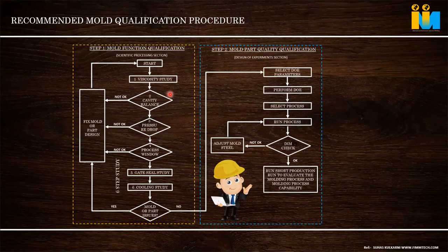Okay, so these are the six steps. In this time, we should not measure the dimension of the part. Generally, we see people hurry to measure dimensions, even when the gate itself is not okay. If it's not okay, they start measuring and saying okay. For a semi-crystalline material, if you do this, it will be a fully devastating result. Because after you change the gate dimension again, the total dimension of the part will change, since it is a highly crystalline material. We should not do that.